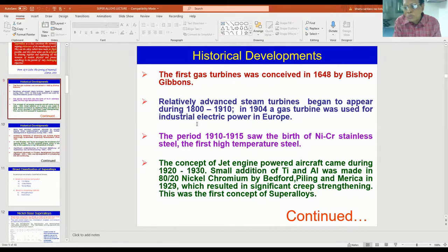Small additions of titanium and aluminum were made to the nickel chromium stainless steel in 1929. This addition has brought some amount of significant creep strengthening. This was the first concept of superalloys, that is, around 1929, the first superalloy was developed by adding titanium and aluminum. This titanium and aluminum combine with nickel to form a strengthening phase that is known as gamma prime. Sometimes we add niobium and tantalum. Those combine with nickel to form the phase known as gamma double prime phase. These are the two phases which contribute to matrix strengthening, and we will see more a little bit later.